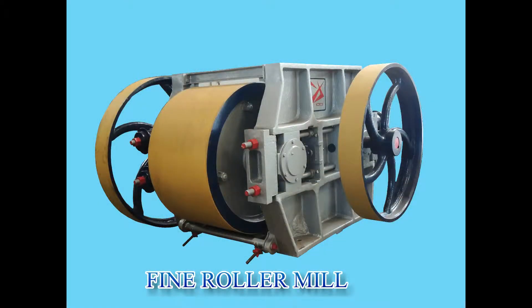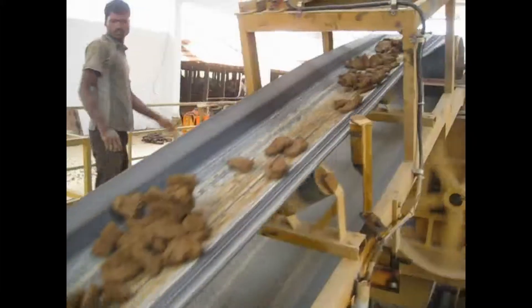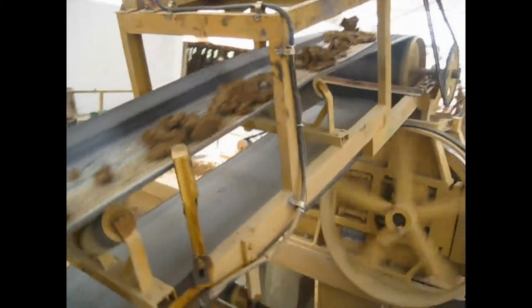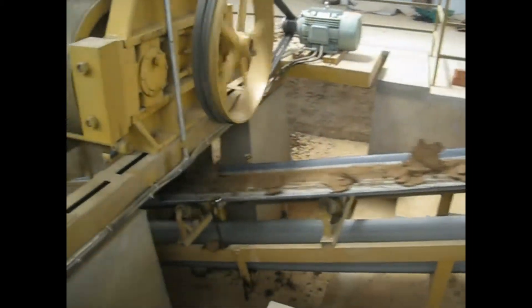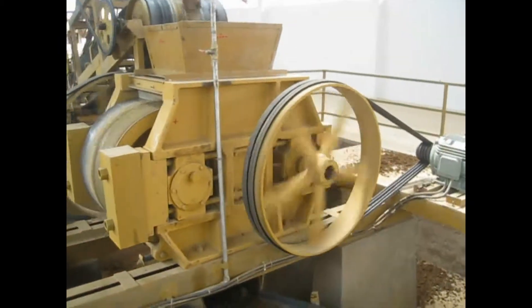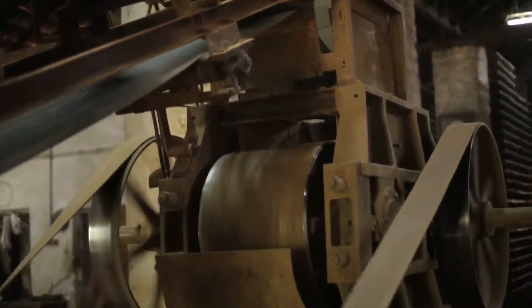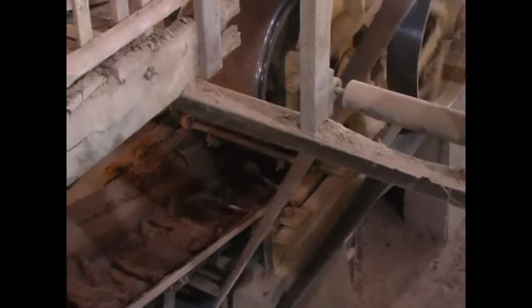The raw materials usually contain crushable stones and hard clay, which needs to be reduced to smaller sizes by feeding it into crushing rollers to facilitate finer grinding. The granules of harder materials are crushed to sizes between 3 mm and less than 1 mm in two stages by differential speed roller mills. This fine grinding process is highly important to maintain quality control of the finished product.